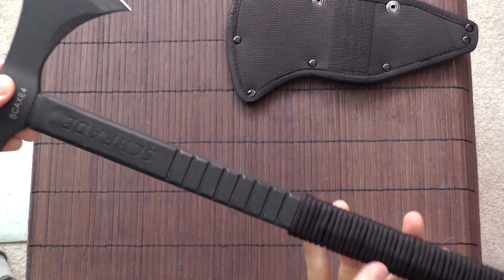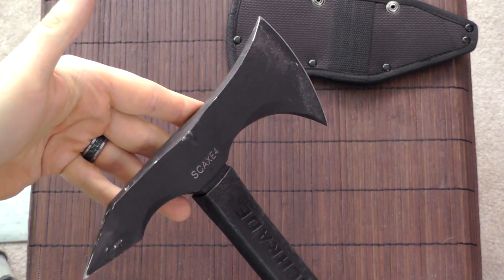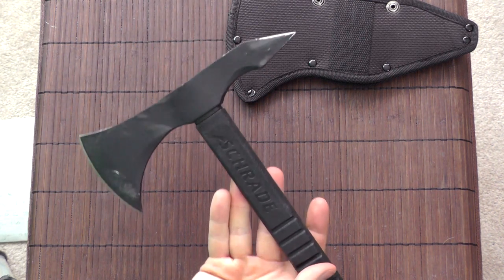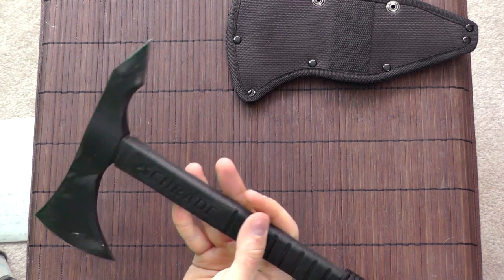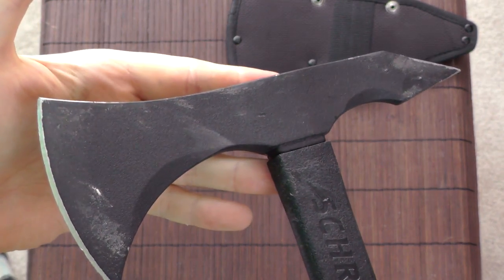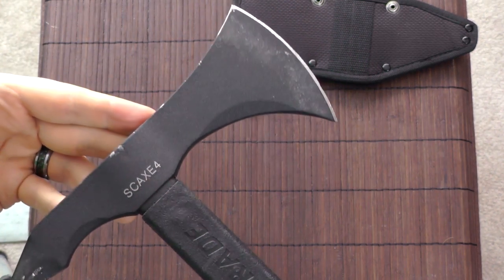It is made of 3CR13 stainless steel, and this is also my main complaint. 3CR13 is a low-end steel — it is cheap and pretty soft compared to other steels. It's just not a great performer. It has slightly higher wear resistance than 420J2, but otherwise it's pretty similar to it, and 420J2 is generally considered to be a cheapo steel, in the negative sense of the term.